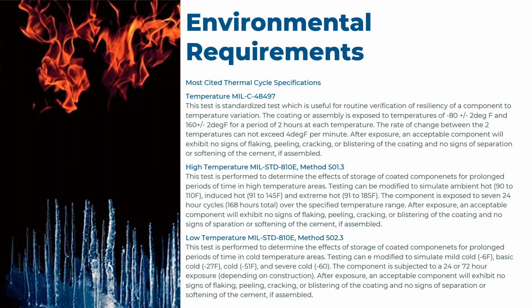One of the most common ones we see is MIL-C-48497. It's a real standardized test, and basically it's 2 hours at the high end and the low end with a 2 to 4 degree step down. You'll see this a lot on polymeric optics that can handle high heat. You'll also see it on cemented or bonded optics. It's not that it's not an aggressive test, it's just more real world.